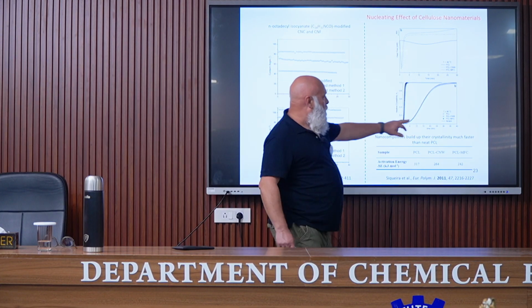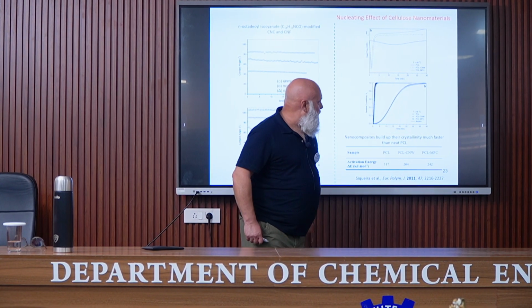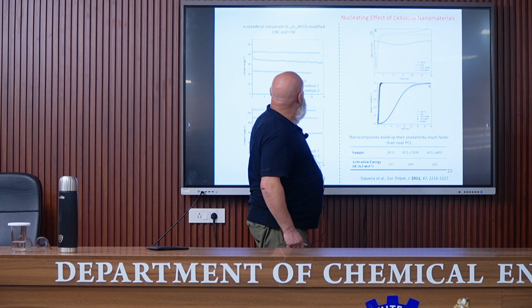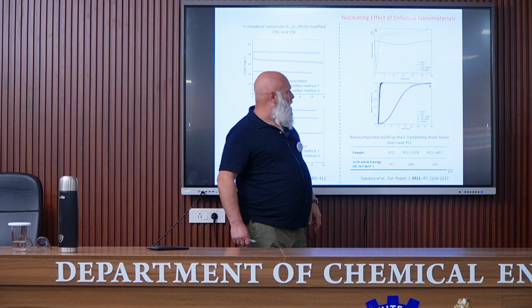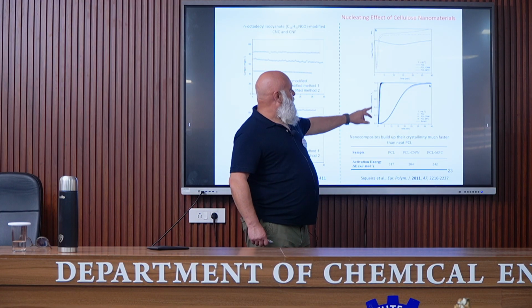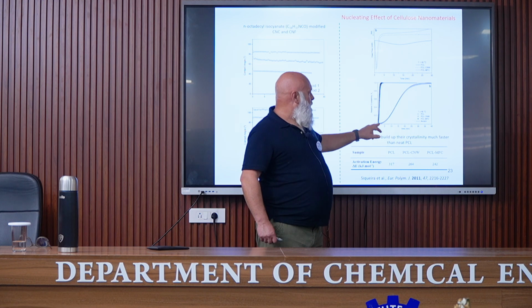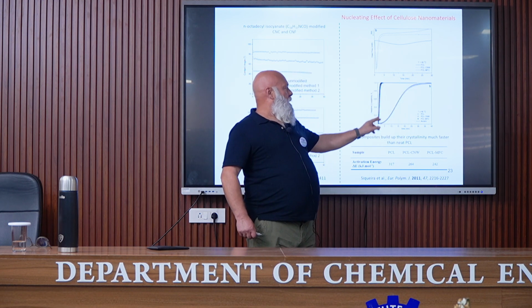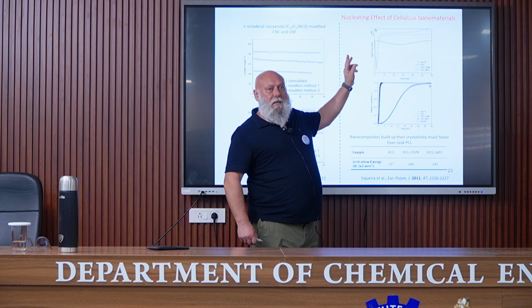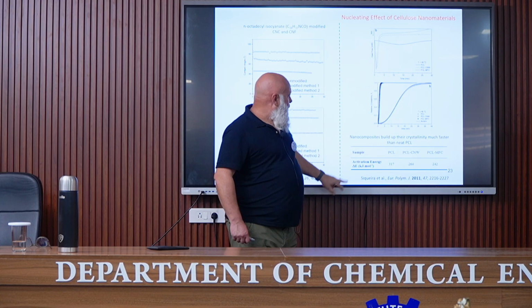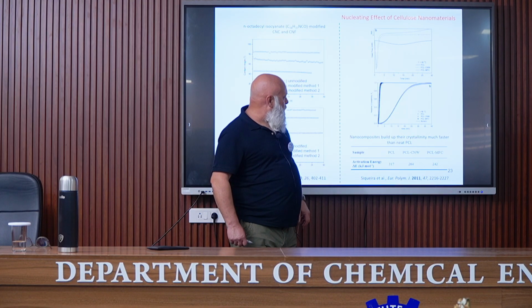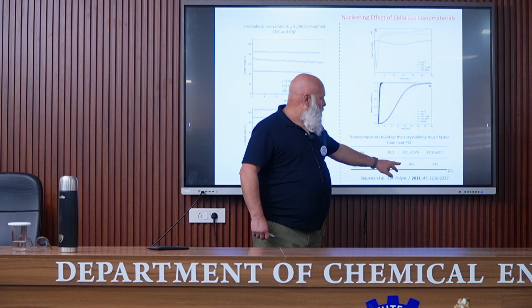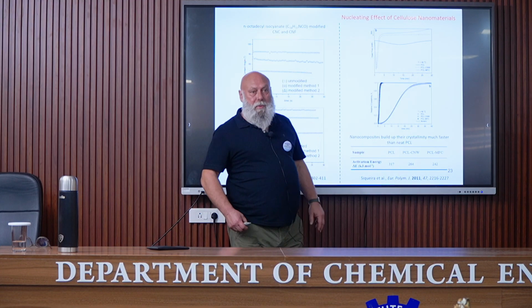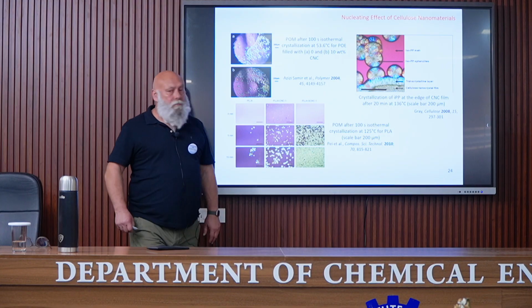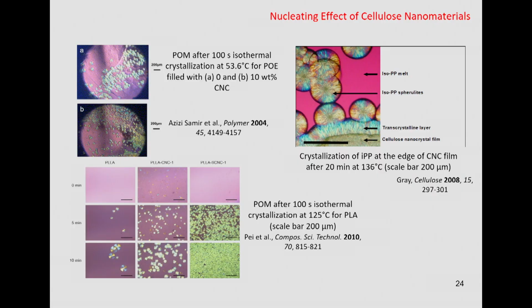So for the pure matrix, and for the matrix containing, I don't remember, maybe 12% cellulose nanocrystals and 12% cellulose nanofibrils, this is the relative crystallinity as a function of time for the matrix and for the composite. You can see that the crystallization is much faster. And it was observed also that the activation energy for crystallization was lower for the composites compared to the neat PLA matrix. We can observe this germination using polarized optical microscopy.